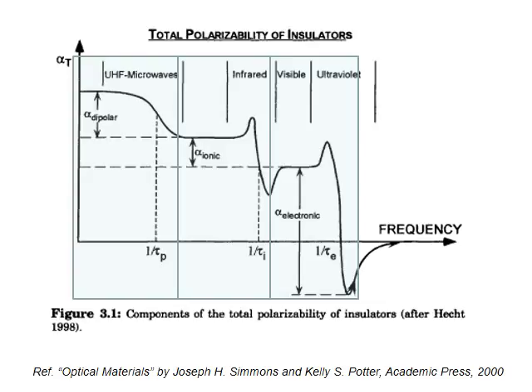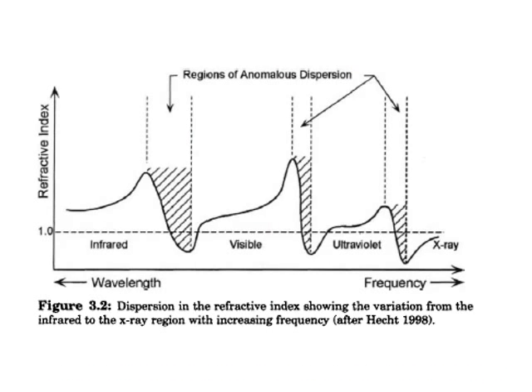This maximizes the phase difference between the applied field and the induced polarization, leading to maximum energy extraction from the wave. The refractive index and absorption coefficients are affected in a way similar to that for the induced polarization, as shown in the figure. Normal dispersion corresponds to a decrease in refractive index with increasing wavelength. Anomalous dispersion refers to the opposite behavior. In other words, in the normal dispersion regime, the higher frequency light will travel more slowly than the lower frequency light.